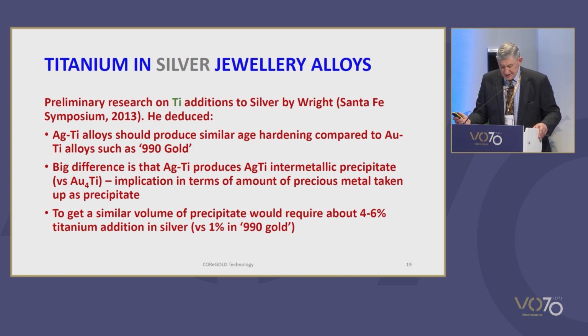A big difference is that the silver titanium system produces the intermetallic phase AgTi as the precipitate compared to Au4Ti for the gold system. This has implications for the volume of precious metal taken up as a precipitate. He also noted that the decrease in solubility of titanium on cooling to room temperature is much less in the silver system compared to the gold system.